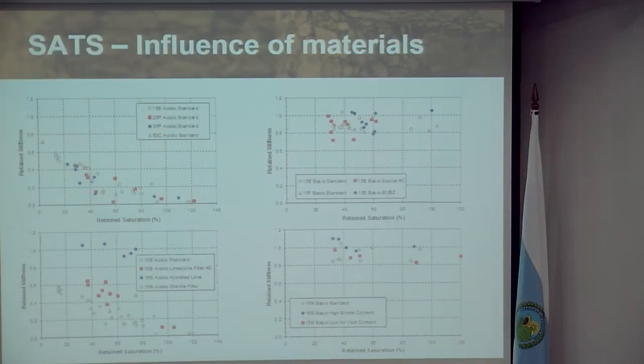The one on the right hand side is the same range of different binders, but this time using a basic aggregate, a limestone type aggregate, sedimentary aggregate. We can see differences there. The bottom left-hand corner is the very first graph I showed you when we started talking about moisture damage, how we could change just very small components, such as the filler, by replacing it with hydrated lime and see the effects of improved moisture damage resistance.